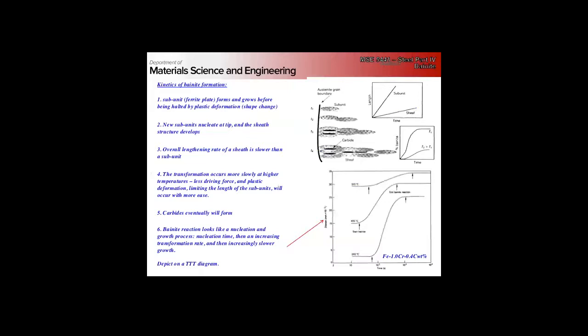involves dislocations that are passing through. We've got a high dislocation density immediately surrounding the lath. So that means that material is significantly work hardening around this little bainite sheath very locally. And basically the energy balance goes wonky, and this subunit gets halted. Then nearby, we have a new subunit that nucleates, forming this sort of sheath